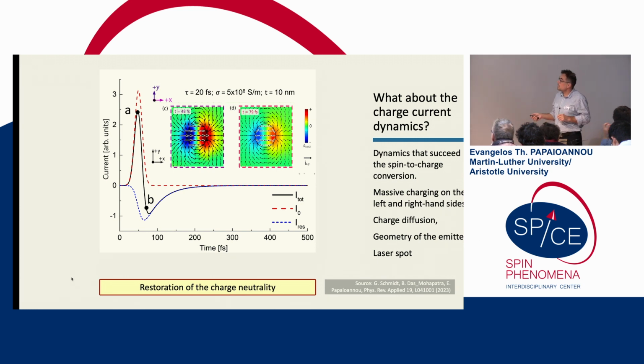So this is what we try to show here with this curve. The total current is what we detect, this bipolar pulse. This is the total current, but it comes as an addition from two parts: the main current induced by the inverse spin Hall effect, and then you have a kind of a response current or backflow current, which is the blue curve. And the convolution of these two currents gives us this shape. And the main argument is that this happens because of this restoration of the charge neutrality.